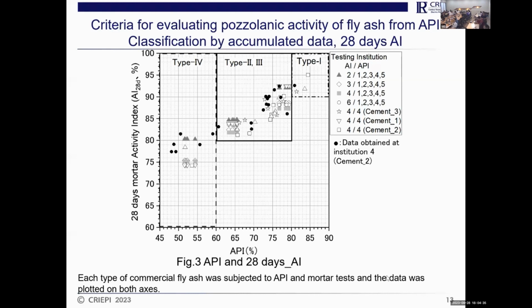In the Japan standard, in JIS, there are 4 types of class from 1 to 4. The lower limit for type 1, which is very high reactivity fly ash, is now 90%. And for type 2 and type 3, the lower limit is now 80%. And last one, type 4, we must determine the lower limit as 60% now.